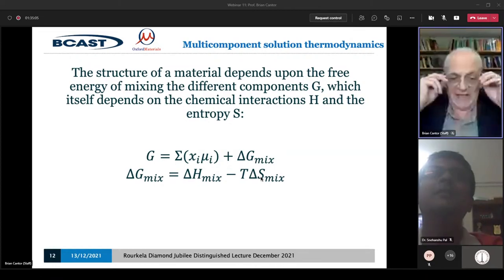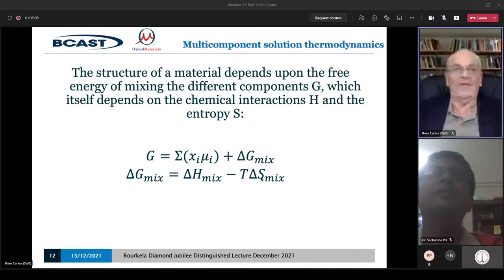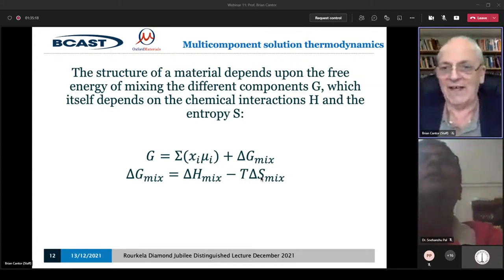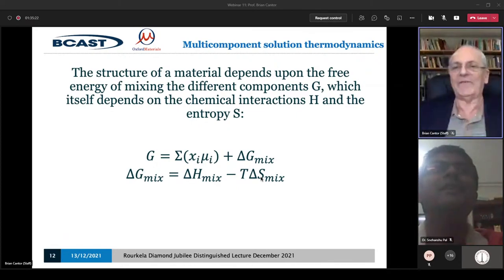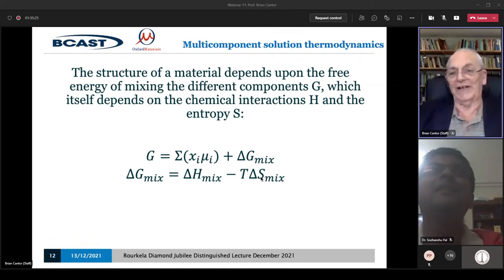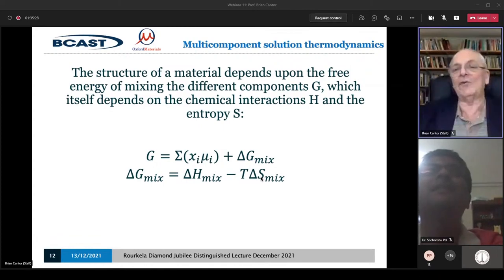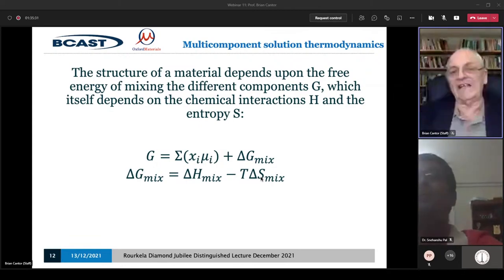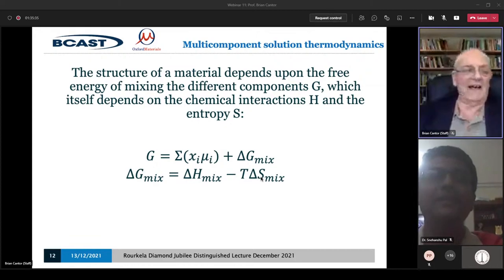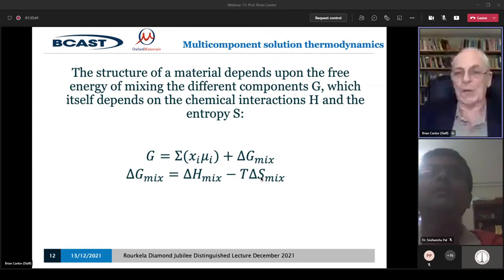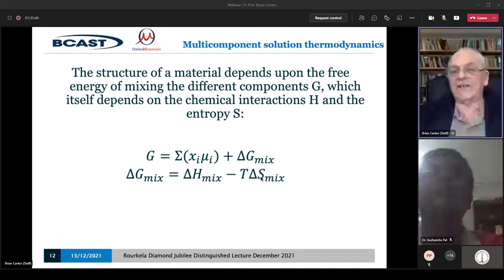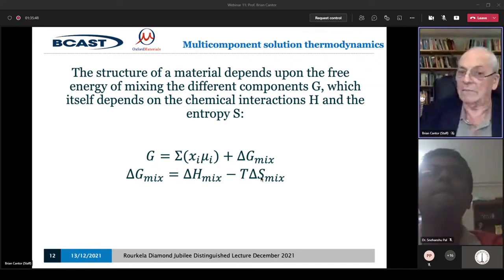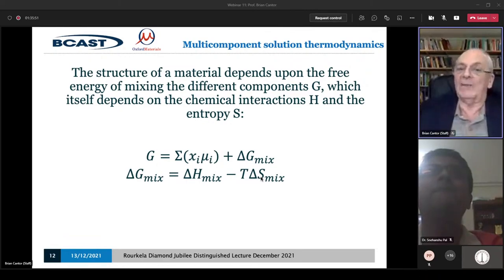So first thing, people were amazed to discover this Cantor alloy existed. And they were, first of all, amazed it seemed to be incredibly stable. You could heat it for long times. It stayed as a perfect single-phase FCC material. Then somebody annealed it for 5 years. I mean, it took 5 years after the discovery for people to discover that it takes more than 3 years at about 800 degrees C to decompose away from being a single phase. Below 800 degrees C, it's stable. It doesn't decompose.